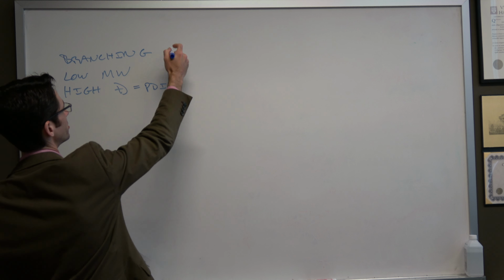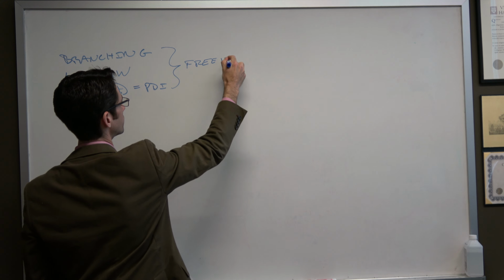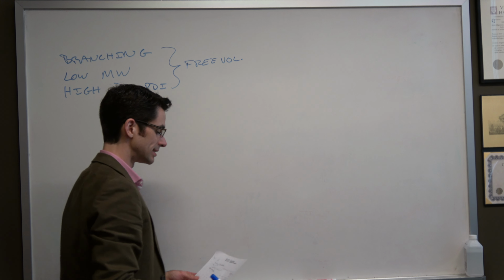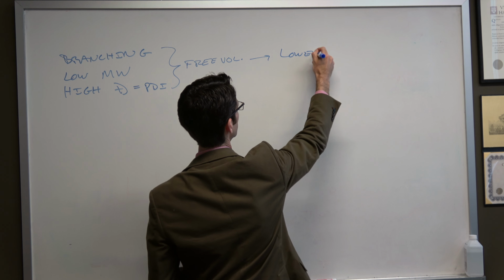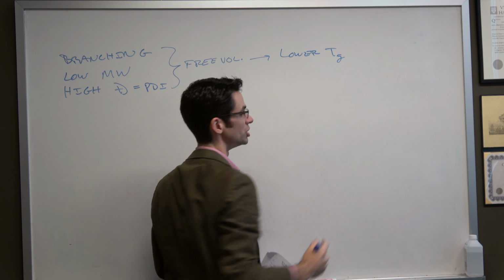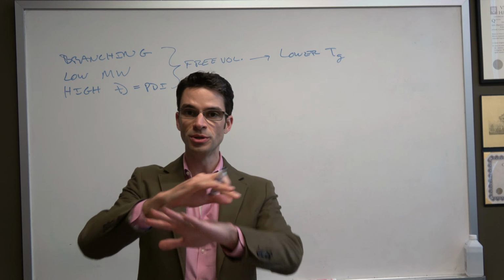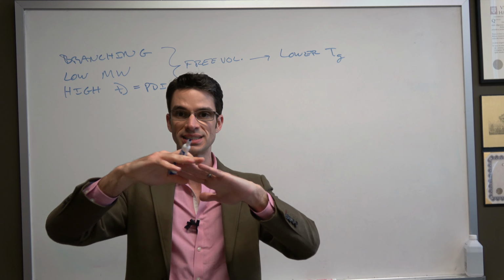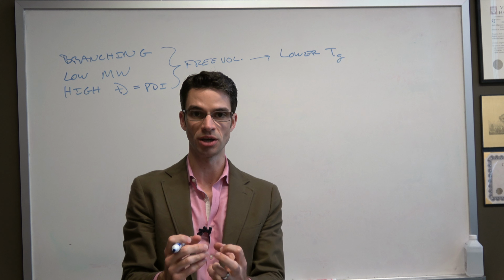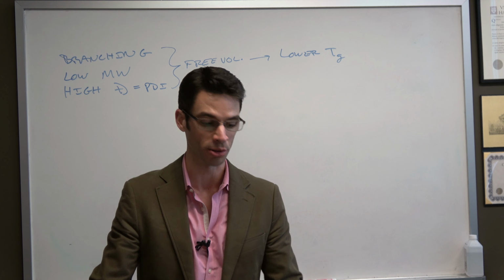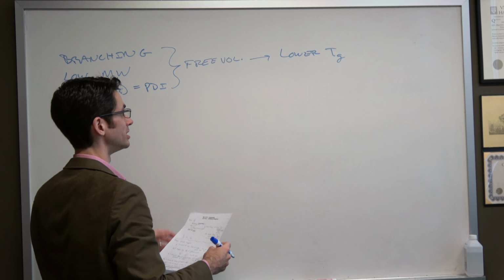And it all comes down to their effect on the free volume. And the greater the free volume, the lower the Tg, so there's less of an activation energy required in order to get two polymer chains in the amorphous domains to slide past each other, where the polymer material goes from a glassy state to a rubbery state as you increase the temperature past Tg.